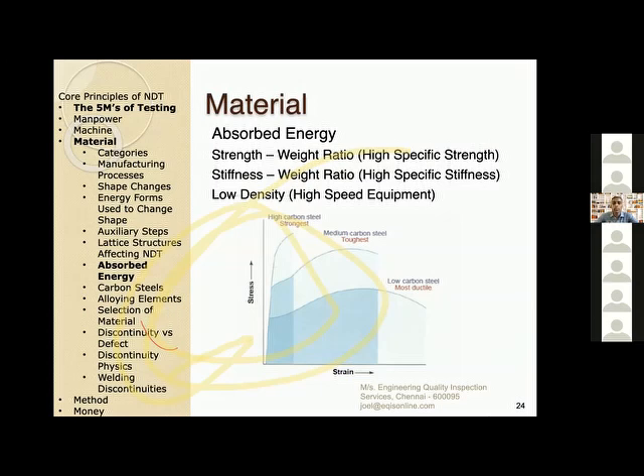So this is a stress strain graph which shows how a low carbon steel, though its stress taking capacity is very low, has a lot of ductile properties, which means it can elongate comfortably for a particular period of time and still get back to its own spot. Whereas if I'm talking about a medium carbon steel, it's going to break somewhere halfway through a low carbon steel. And if I take a high carbon steel, it's more prone to getting cracked. I have seen in physical cases where anything above 25 mm of thickness in carbon steel definitely breaks. It doesn't work out in NDT.